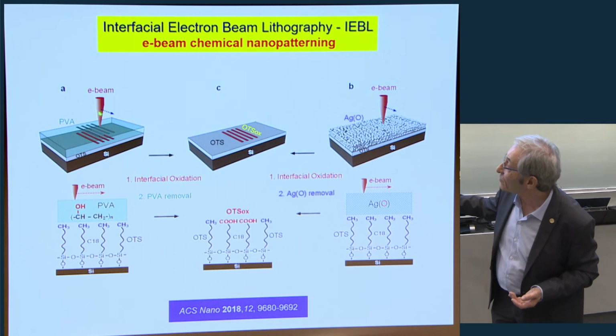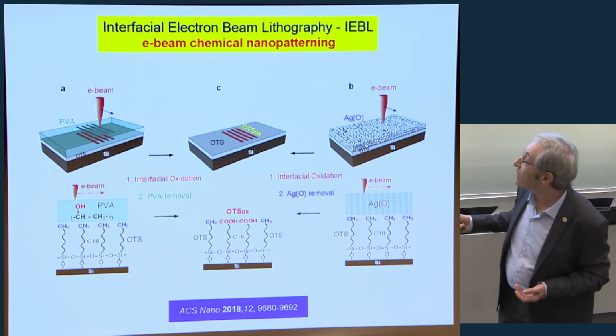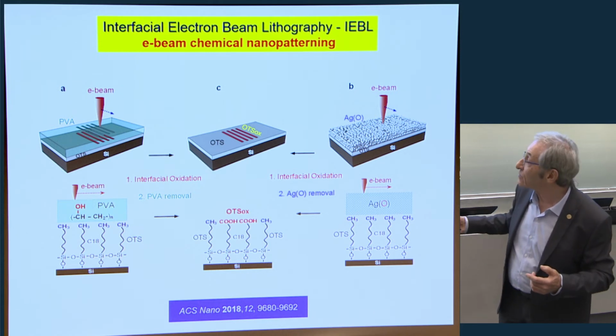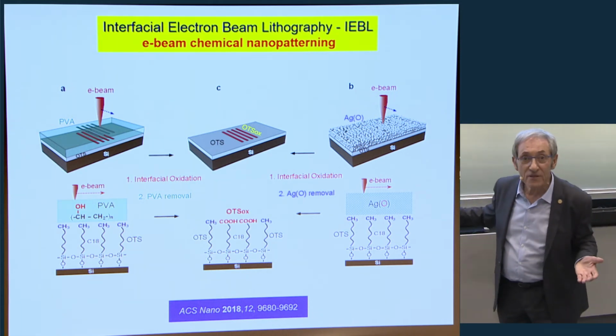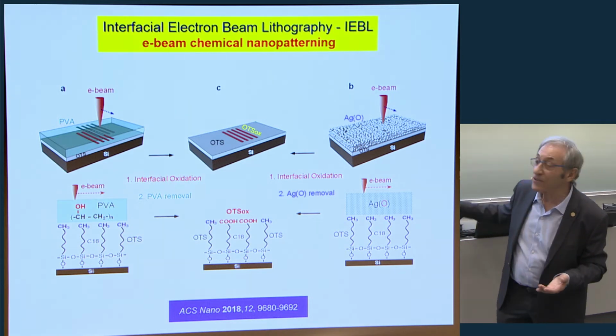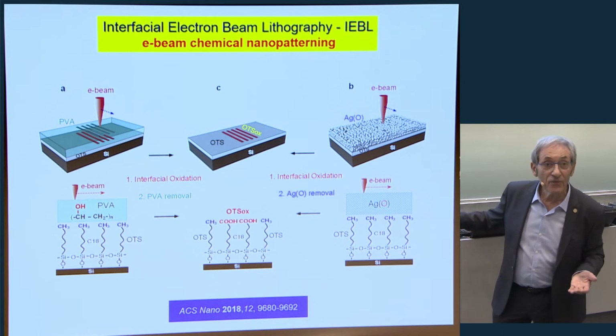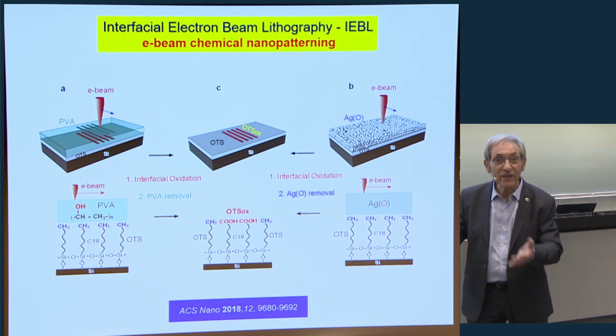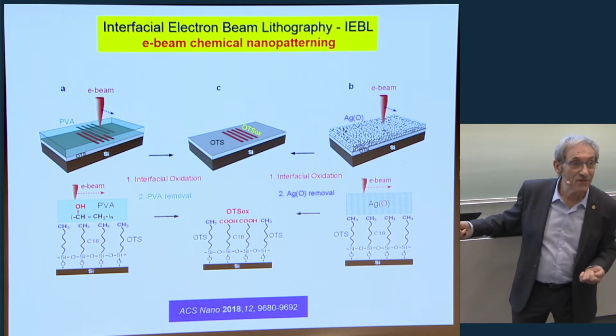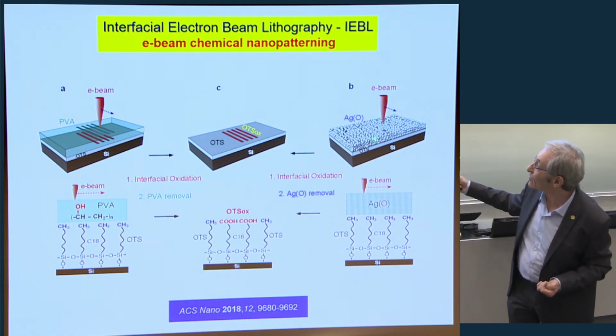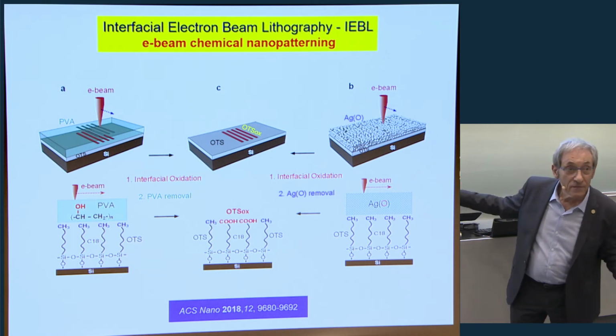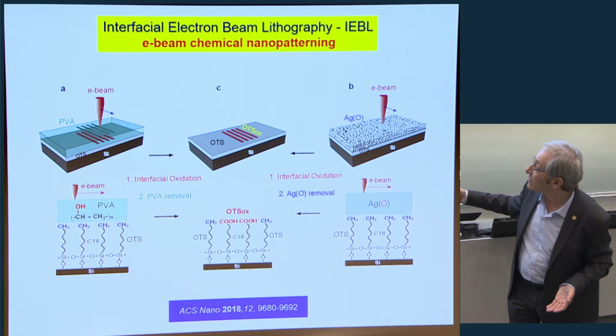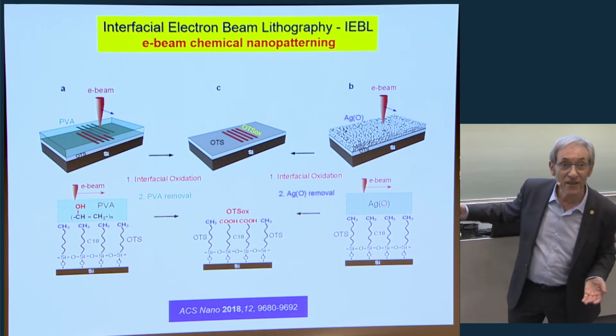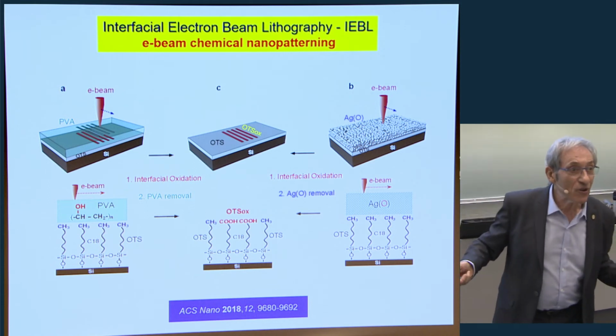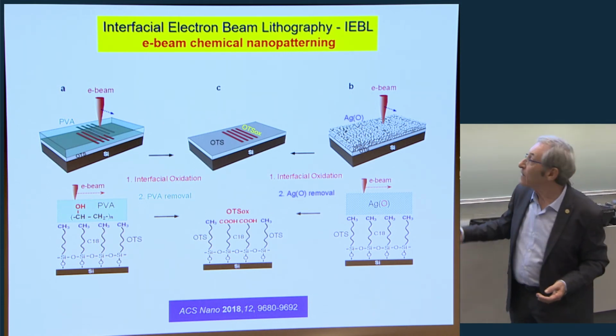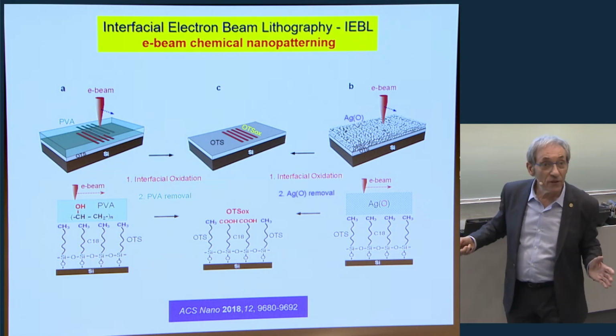So we write with the electron beam, and the reaction occurs at the interface. Then it was found that you can use different polymers and get different reactions. You can even use a thin film of metal that contains oxygen. If you evaporate a thin film of silver and bring it into the air, it gets oxidized, and it can also release oxygen. So you can write on this with the beam. You remove the PVA or the metal, and then you have a pattern we refer to as OTS oxidized. There's no other name for this because you don't have this compound anywhere except on the surface. And then you can write anything you want with the electron beam.